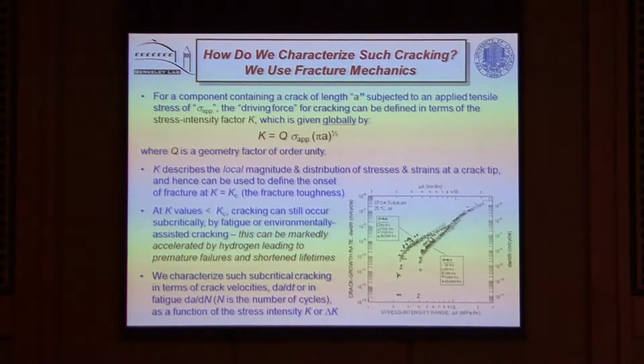And we talk about things called velocity-K curves, V-K curves. This is the velocity of the crack. In this case, it's fatigue crack growth, da/dN, the rate of change of crack length with cycles, as a function of this stress intensity factor. And in fatigue, we talk about a delta K because the stresses vary over the cycle. And so it's important to be able to characterize these velocities in various different hydrogen environments and to quantify this in terms of a stress intensity. And these V-K plots then become the basis of life prediction because we can integrate these plots from some initial crack size to a final crack size defined by the fracture toughness and predict life.